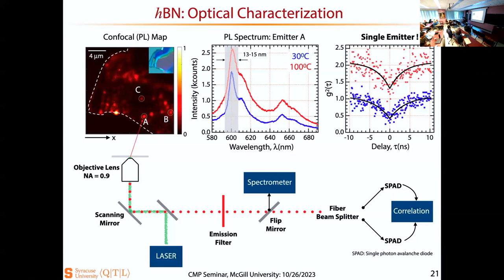It was really a very broad spectrum. It was not a zero phonon line. So we physically go and look at the spectrum at each and every pixel. The moment we see this kind of emission spectrum, we know from our experience that this is a single photon source. But then we also do a correlation measurement, which I showed, the HBT measurement, to really quantify that those spots are indeed single photon sources. We do that.